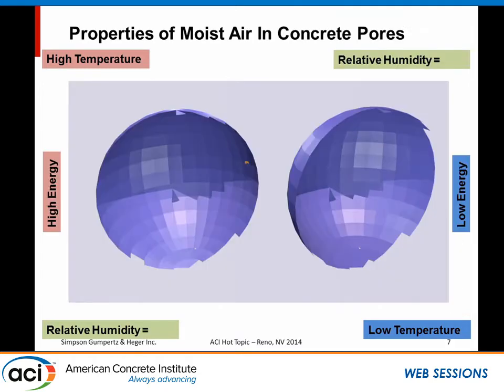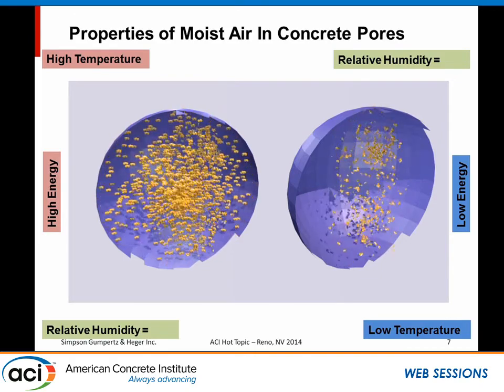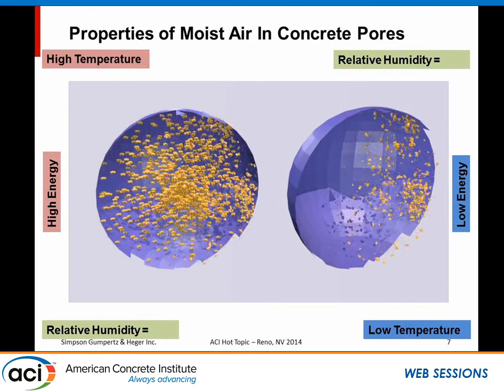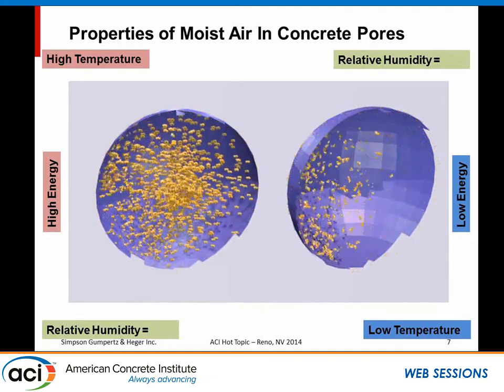It's a different world inside the concrete, because inside we have a lot of little pore structures — little spheres. Water is very attractive; if liquid water really wants to stick to things, that's how we get capillary flow. These pores are connected by capillaries where liquid water and some vapor transfer. If we have high temperature, we have more energy and get more vapor pulled up. If we have low temperature, we have less vapor in those little pore spaces. But in fact, we have exactly equal relative humidities in both situations.